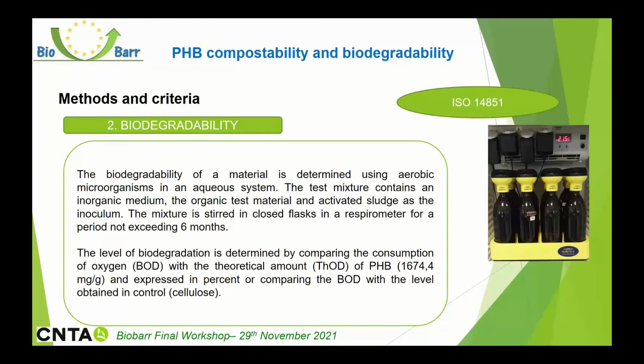Secondly, biodegradability is focused on quantifying how long is necessary for the material to be consumed by microorganisms. Cellulose, a recognized biodegradable material, is used as reference, and the assays compare the oxygen demand, BOD, of microorganisms using the tested material with that using cellulose, and with this the theoretical consumption based on its chemical formula.